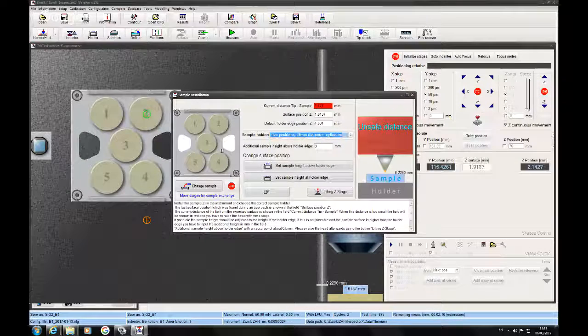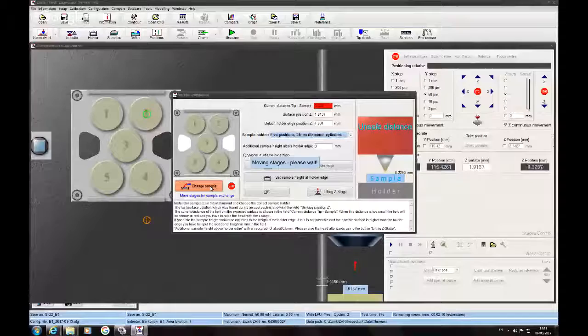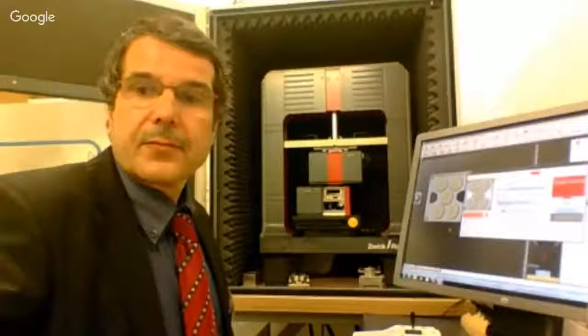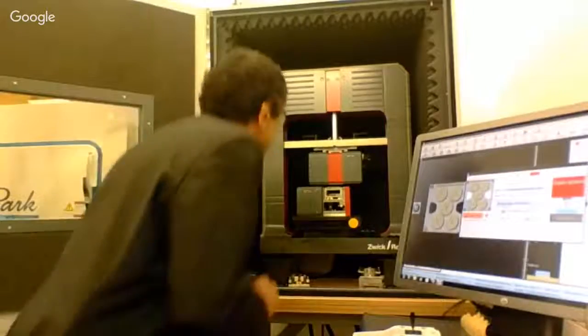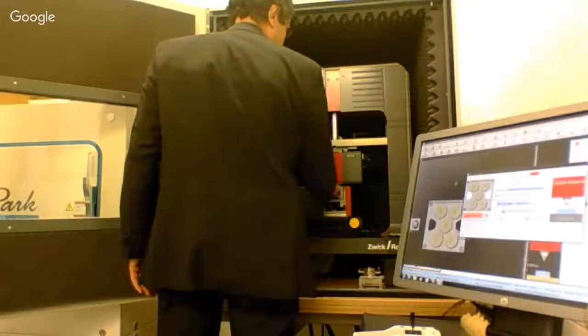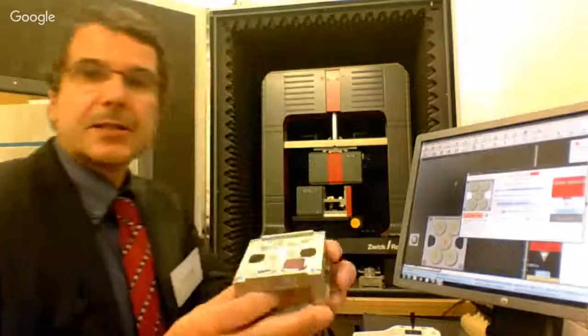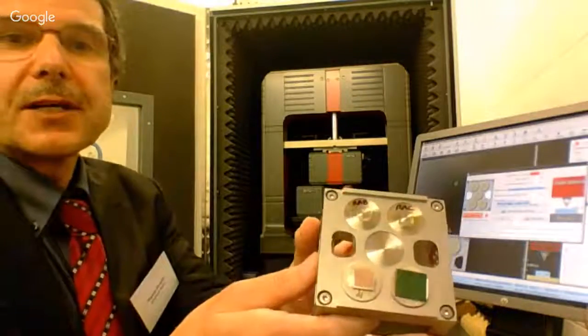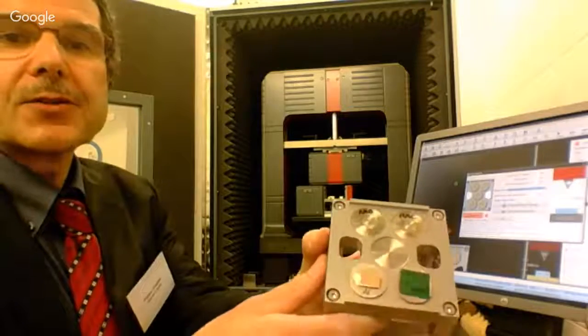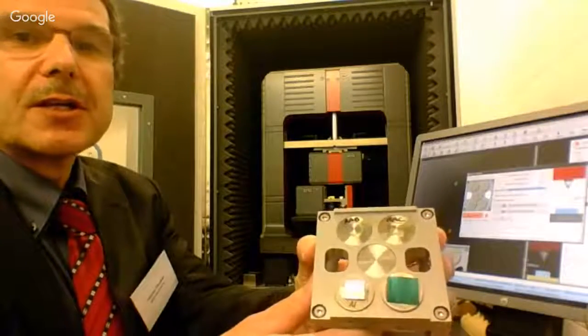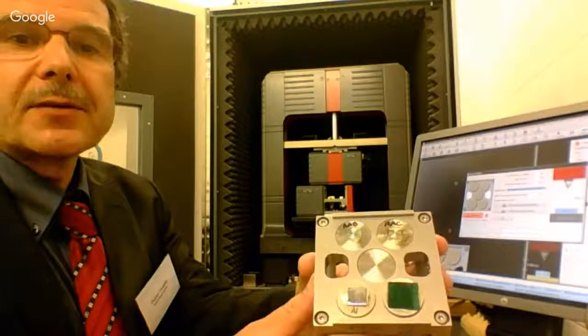At the moment, we use the holder with 5 positions, which is the standard holder, and which also allows a measurement of the contact resistance between tip and sample. To change the sample, we have to go in front. You can see here the sample holder with 5 positions, and 4 of them are used at the moment. One is fused silica, one sapphire, silicon with an oxide layer, and aluminum.